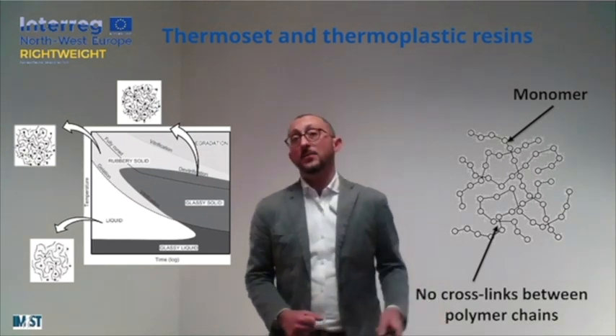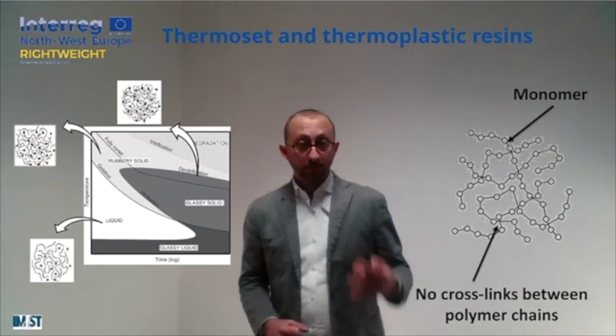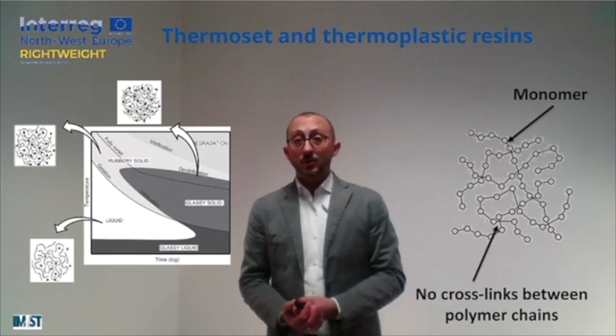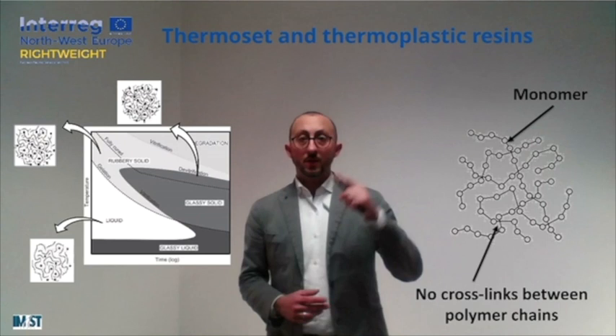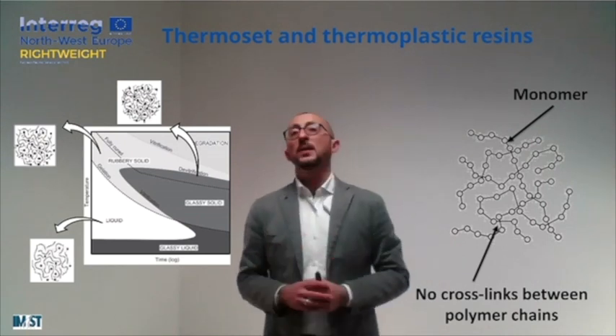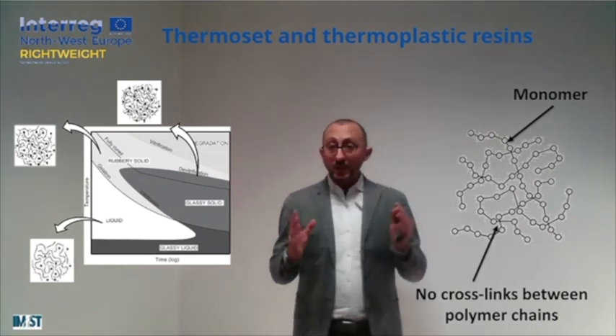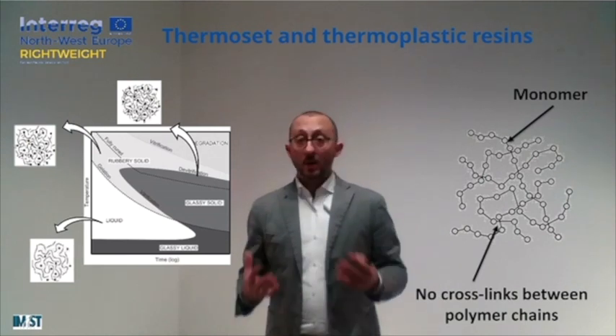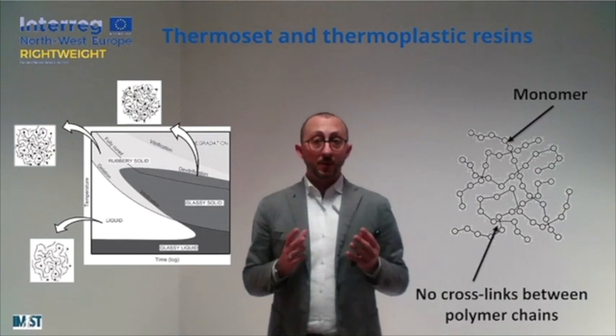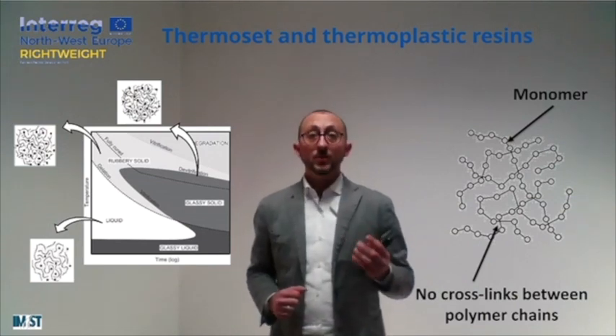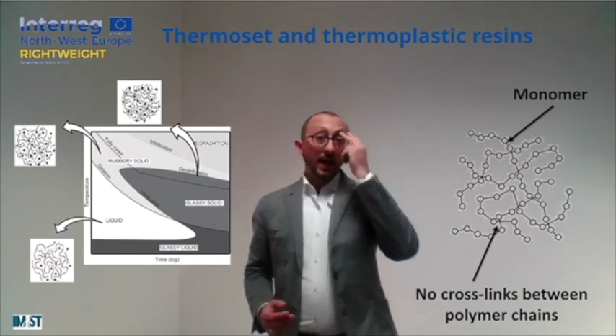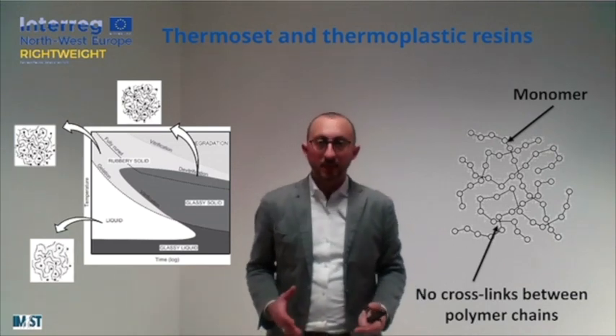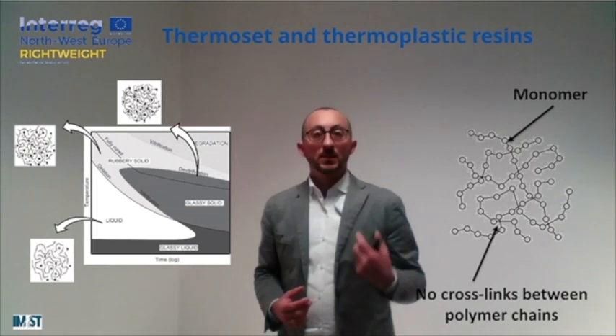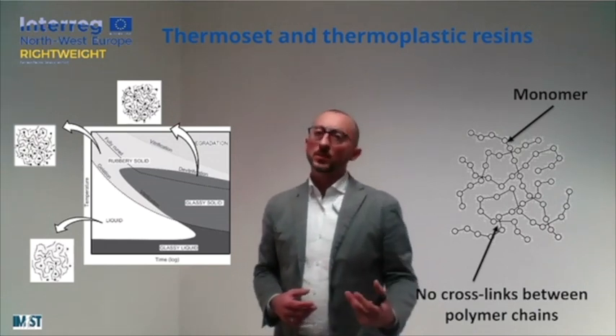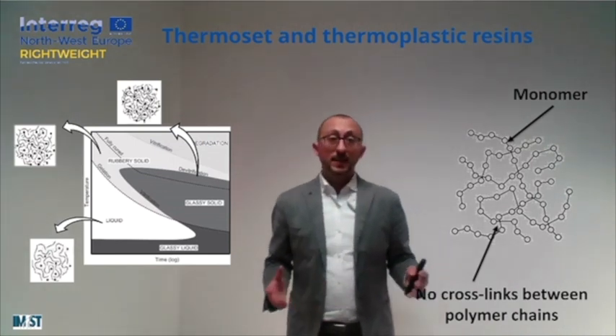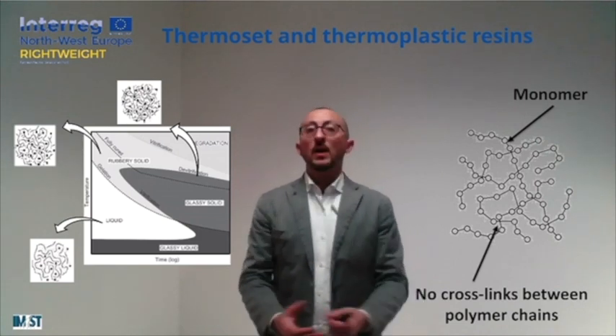And differently from what typically happens on gelation, this transition is not a one-way transition. We can go back and forth, just calibrating our temperature. So, to summarize, when we are dealing with a thermoset resin, if we want to improve our properties, we need to activate the curing reaction, heating our material. And what is particularly interesting when we are processing this kind of resins is that the viscosity of these resins at the beginning of the process is typically quite low, meaning that they can easily flow through our preform and wet fibers.